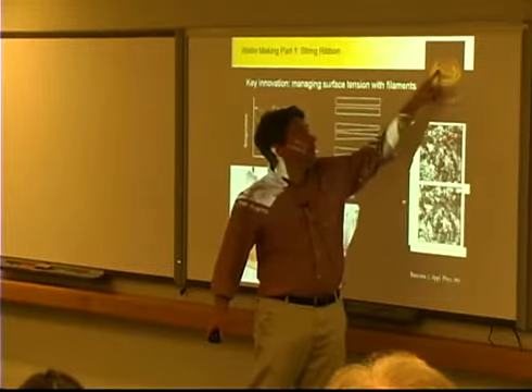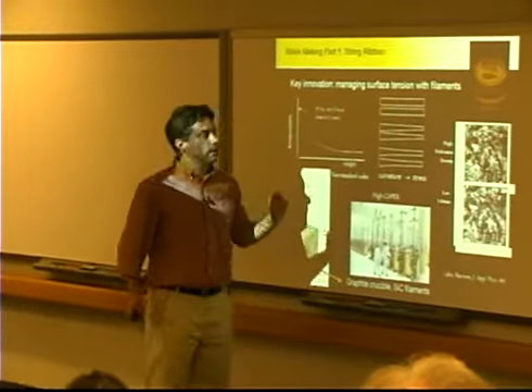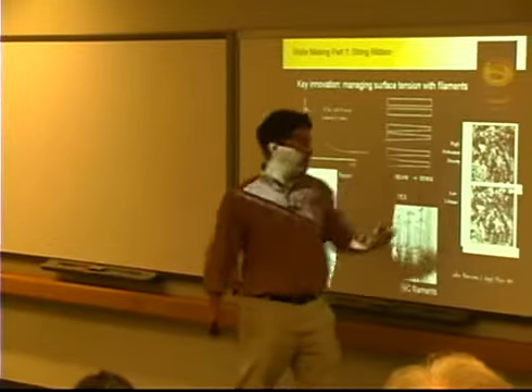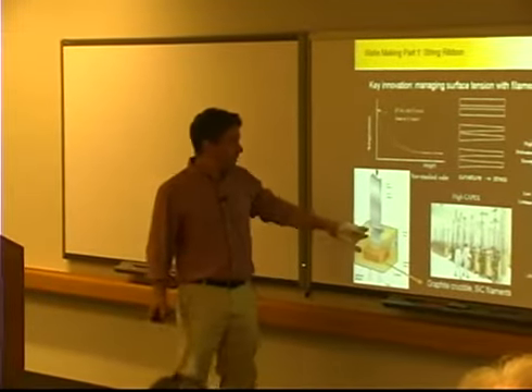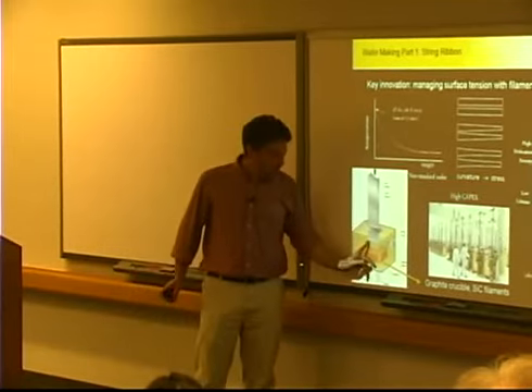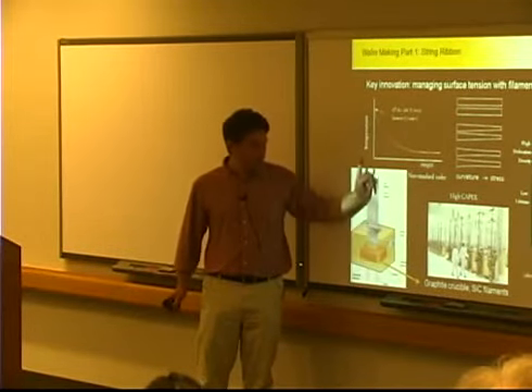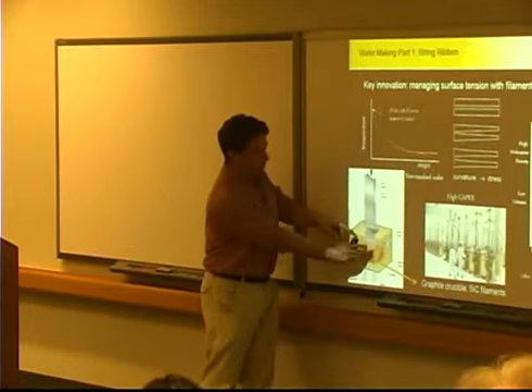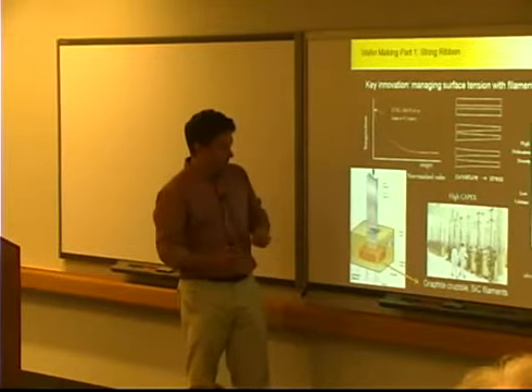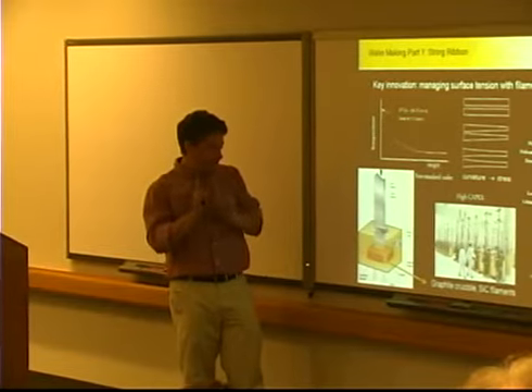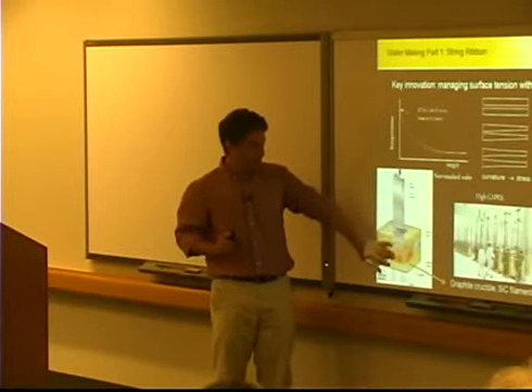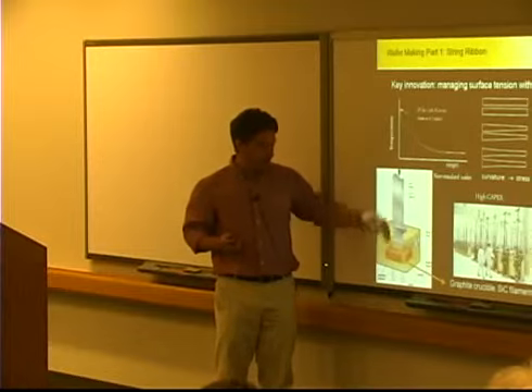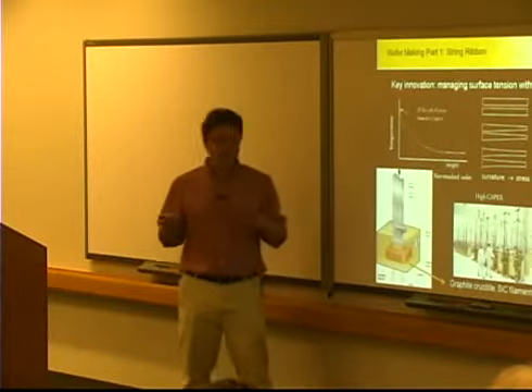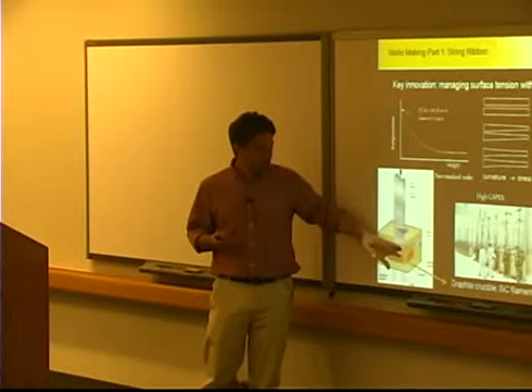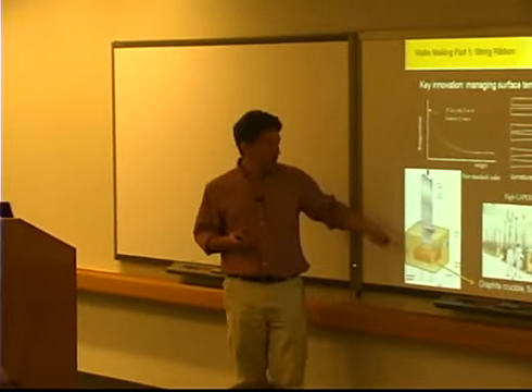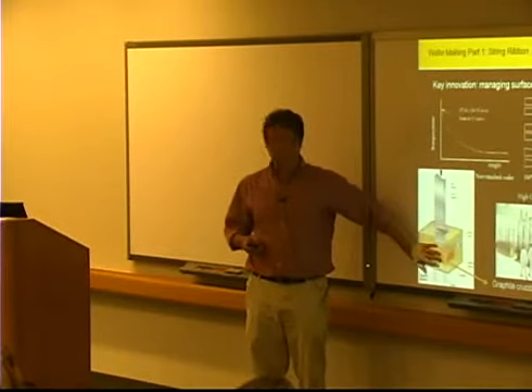And then the bright line here is where it's solidified, and so it's more emissive, and then it cools down relatively quickly. The tricky thing about this process is that you're trying to extract your heat more or less back up the wafer, but at the same time you're moving the wafer up, and these two vectors being parallel more or less limits the speed that you can grow to the rate at which you can extract heat. And so you have to try to cool more and more aggressively right down close to the liquid itself.